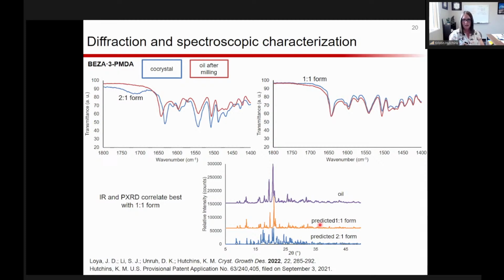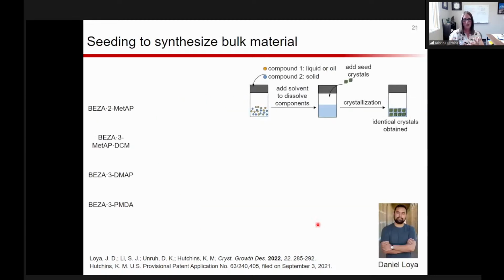And so how did we actually isolate that form? Because when we first did our milling and our slow evaporation, we got that 2-to-1 form. But clearly we have another form in the mix. And so at that point, now that we had gone through this path of milling and slow evaporation and we were able to get co-crystals, we were interested whether there was any way that we could use those co-crystals we had in hand, go back to solution methods and make the material in bulk directly.